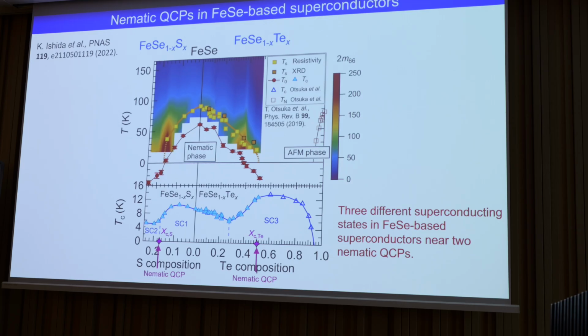So then we want to discuss the impact of this nematic QCP on the superconductivity phase diagram. This TC dependence looks quite interesting. First, you have the first dome, which we call SC1. Outside this nematic QCP on the sulfur side, the TC gets reduced, to about 4 Kelvin, and we call this SC2. We have another superconducting dome with the highest TC here, which we call SC3. So it looks like we have 3 different superconducting phases in this single family.